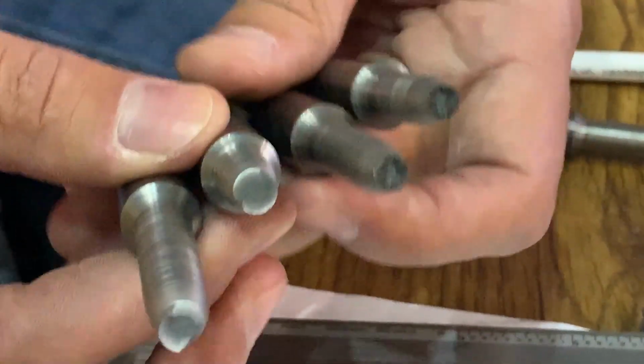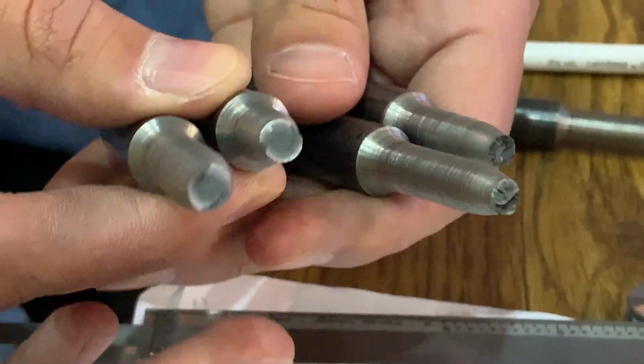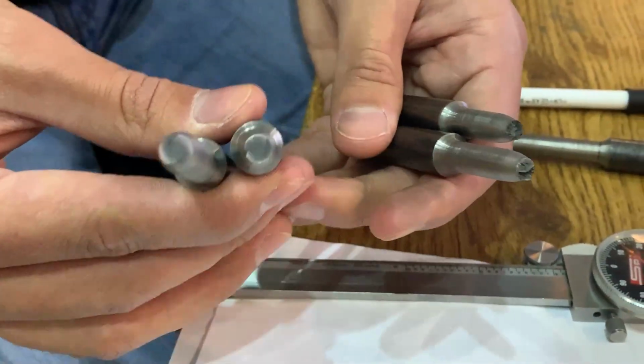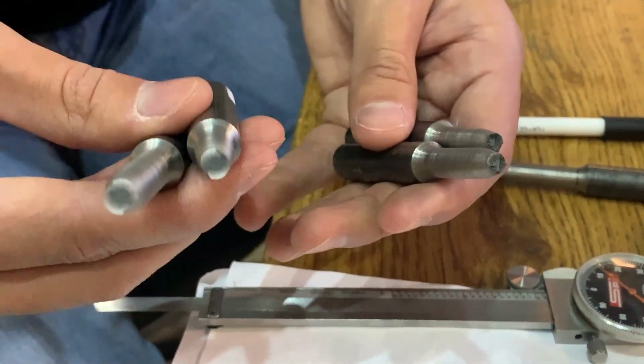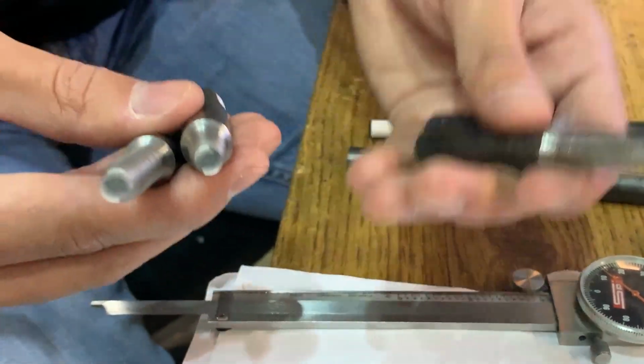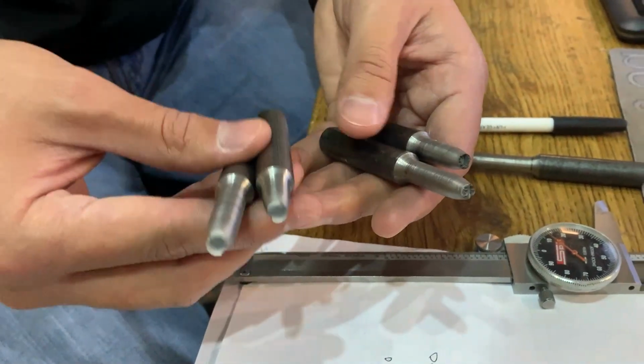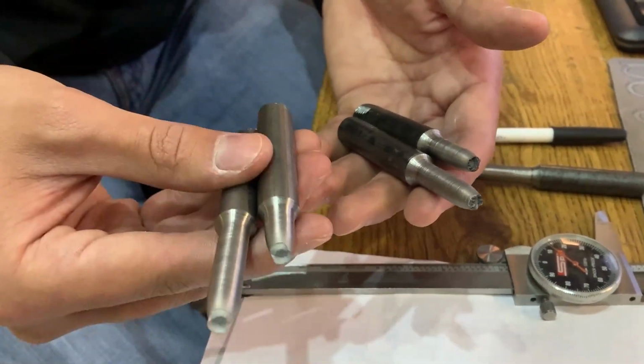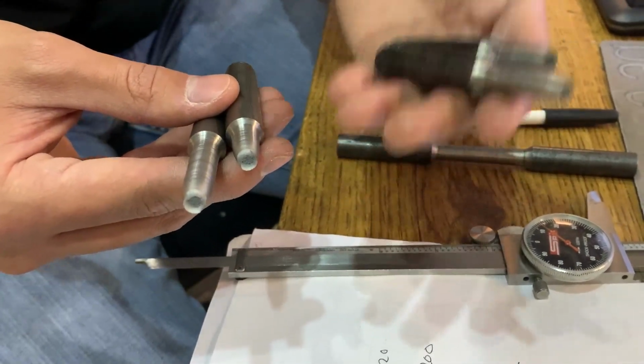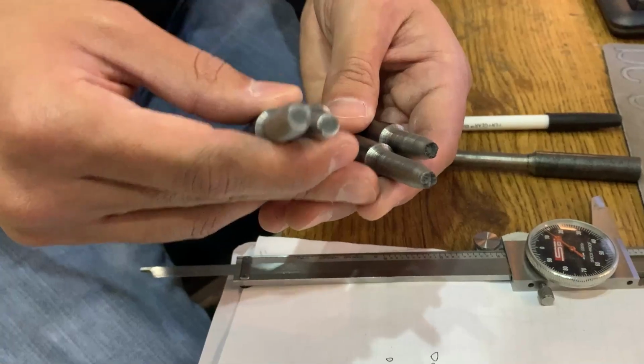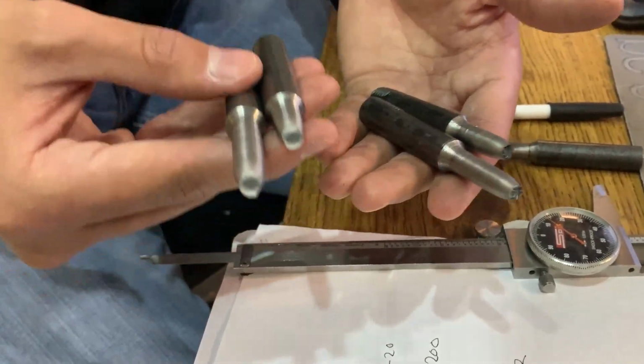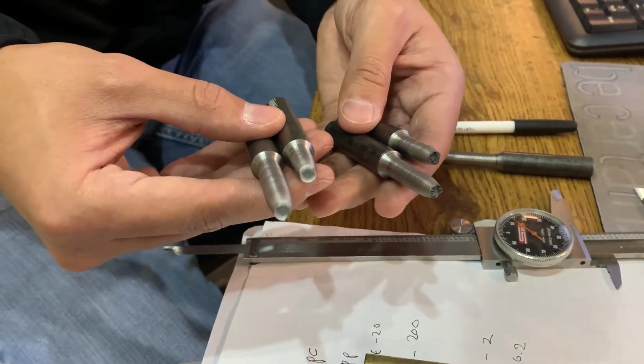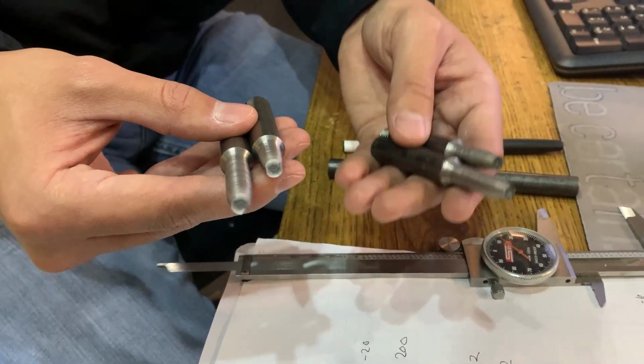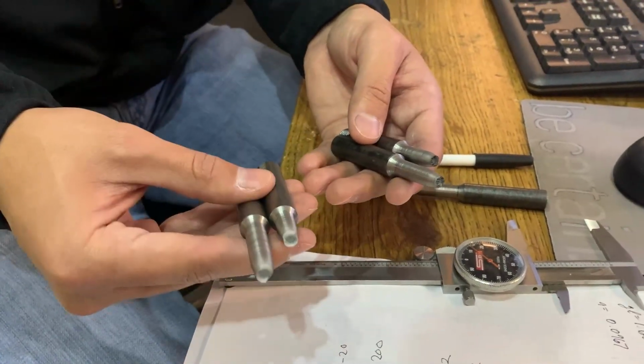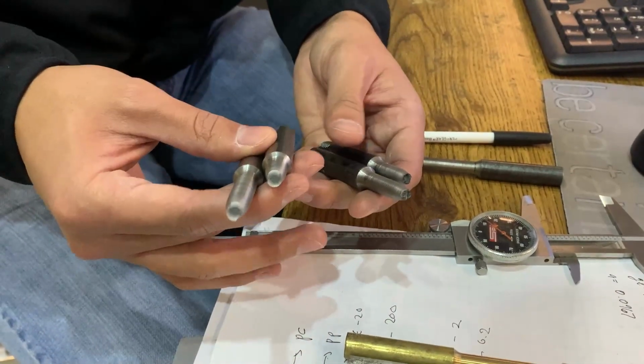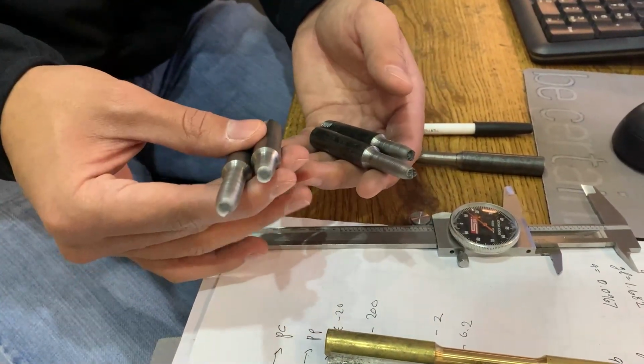And the difference between the two, they're both steel. Both are comprised of iron and carbon mostly, but the determining factor on their fracture, on whether being ductile, which is a little bit more elastic in nature than brittle, is the carbon content. Our carbon content is 0.18% by weight for 1018, and for 4140 it's 0.40% by weight. So the consequence of adding carbon to the steel is that we get a higher ultimate tensile strength for 4140 than we do for 1018, but as a result the material becomes more brittle as opposed to a milder steel like 1018.